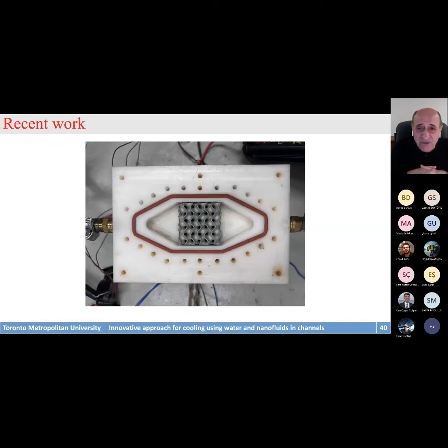So finally, to finish my presentation, this is the block of porous material, which was designed with the help of the architecture department. They designed it in such a way that it allows flow to penetrate, and the porosity in this particular one is found to be equal to 0.7. We are conducting the experiment, as you can see, studying the flow inside this. And then we did two types. We did aluminum printing. So it is 3D printing for aluminum and for silver.